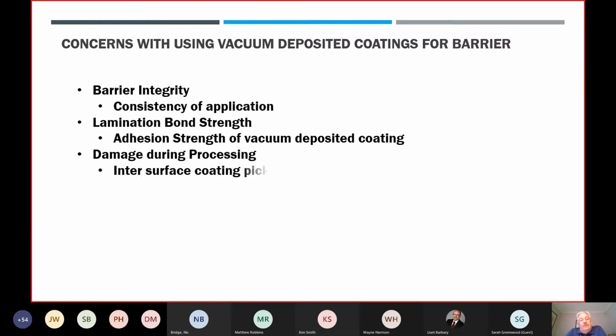And this is the one that also always causes worry. These coatings are quite fragile. When you unwind the roll, you may have high points where you have anti-block agglomerates in the film, and you will get pick. And then if you had a film that's got a lot of these picks, you would hold it up to the light and you would get a starry night effect, where lots of pinholes in the vacuum deposited coating. And what that does is it is a great detriment to the barrier. Then you get physical damage, scratches and scuffs where the coating is removed. And again, that will significantly cause a deterioration in the barrier.